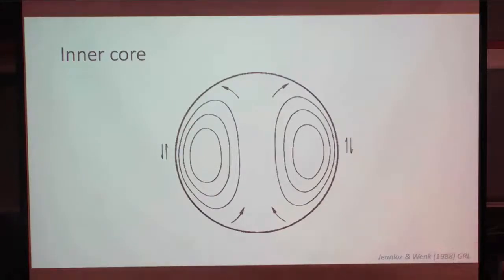The idea of inner core convection has been around for a while. The same group calculated the thermal conductivity of solid iron and found it to be even higher. That very high conductivity makes it very difficult for the inner core to convect, actually. I think this is probably unlikely because the conductivity is so high; it makes it so efficient at transporting heat by conduction alone.